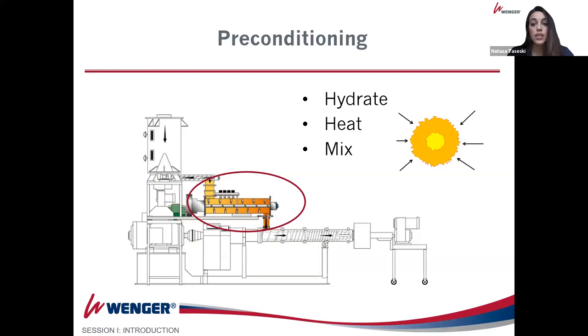As you see there, there's an image of a granule with a light yellow center and an orange sphere on the outside. This essentially shows the diffusion process of water being able to penetrate the particle. So the extrusion process is a very short cooking process, 15 to 30 seconds. With the addition of the preconditioner, you have about 1 minute to 2 minutes or longer, as can be adjusted on the process, to allow the materials to mix with water or other liquids to hydrate. And also you may be able to introduce heat as well if you need to do additional cooking before going into the extrusion process.